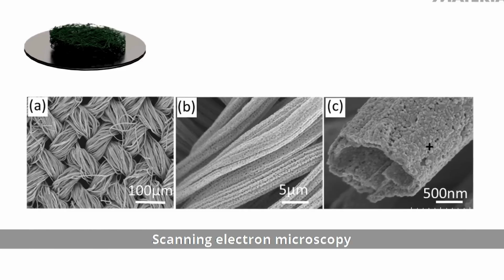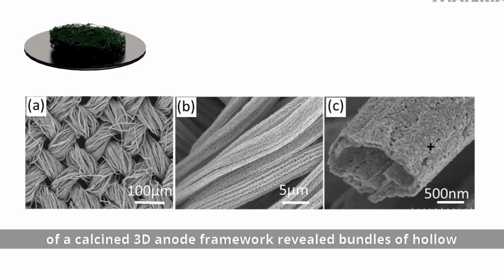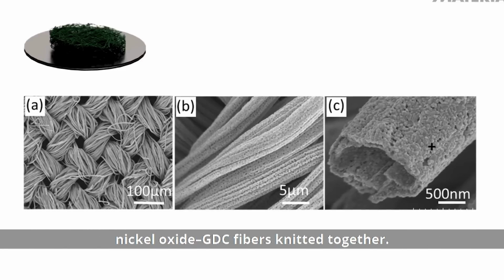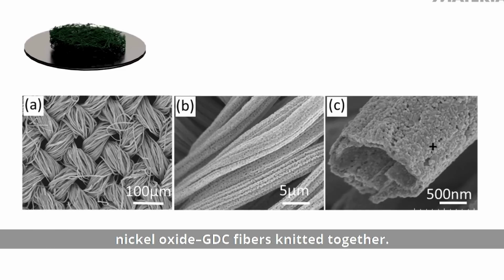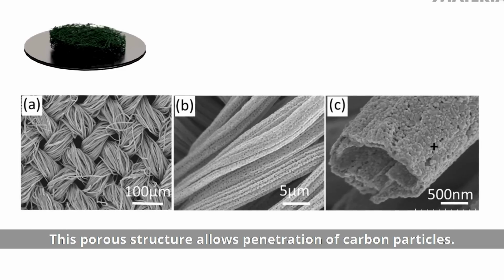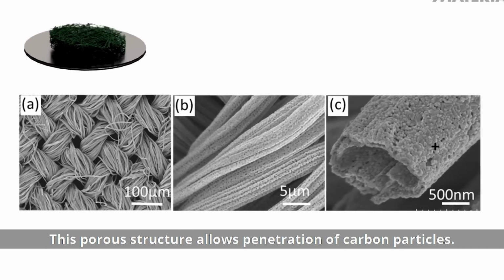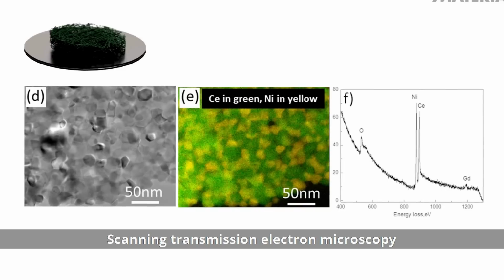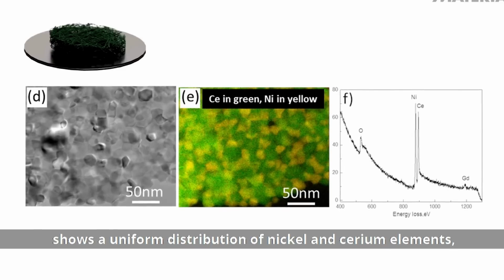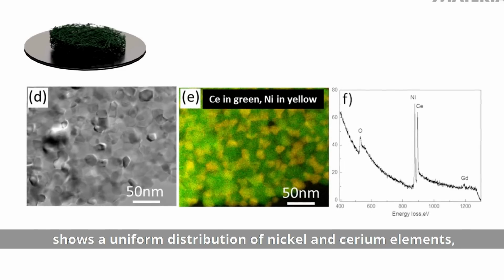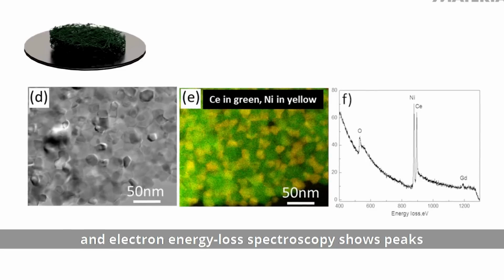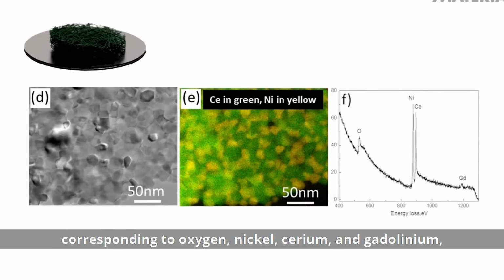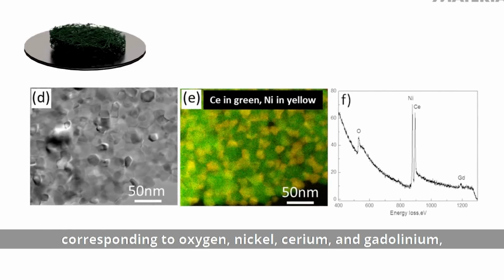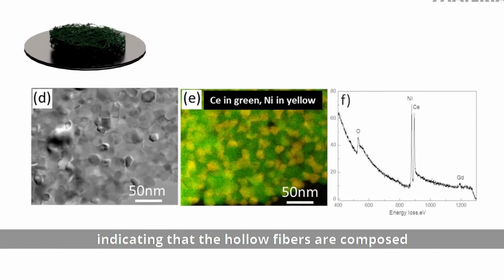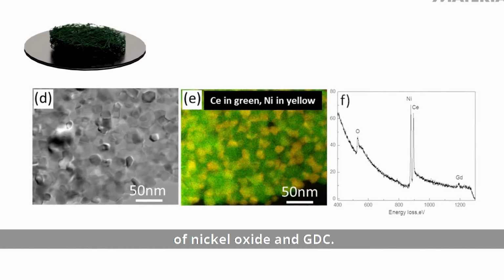Scanning electron microscopy of a calcined 3D anode framework revealed bundles of hollow nickel oxide GDC fibers knitted together. This porous structure allows penetration of carbon particles. Scanning transmission electron microscopy shows a uniform distribution of nickel and cerium elements, and electron energy loss spectroscopy shows peaks corresponding to oxygen, nickel, cerium, and gadolinium, indicating that the hollow fibers are composed of nickel oxide and GDC.